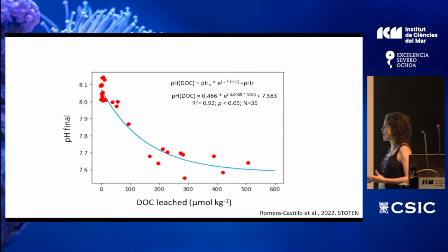Putting all these results together in a plot showing the pH at the end of the experiment versus the amount of DOC leached by plastic, we found that there is a correlation. That is an exponential correlation, an exponential equation, showing that the pH decrease depended on the amount of DOC leached by plastic. So we found that this curve reached a plateau at 7.6 units of pH, and that the highest decrease experienced was 0.5 units.